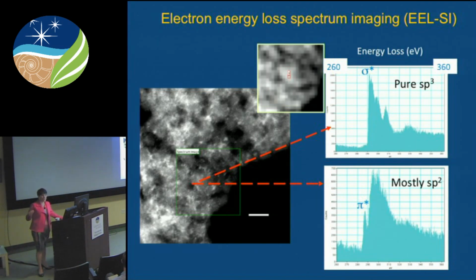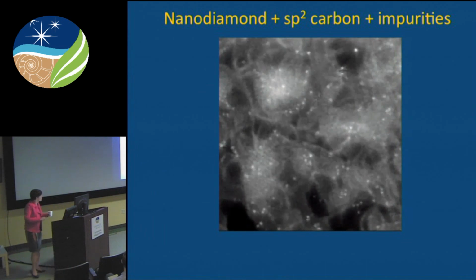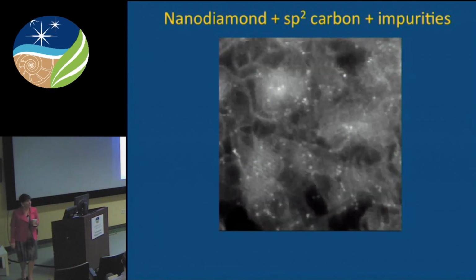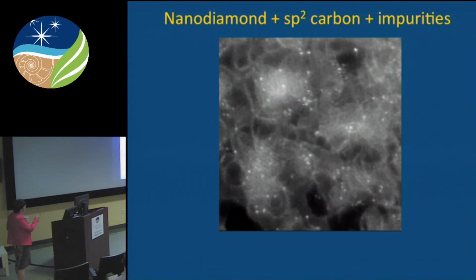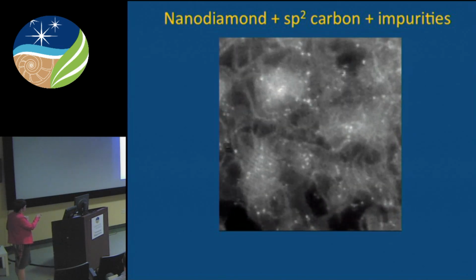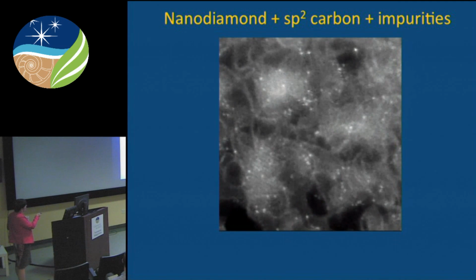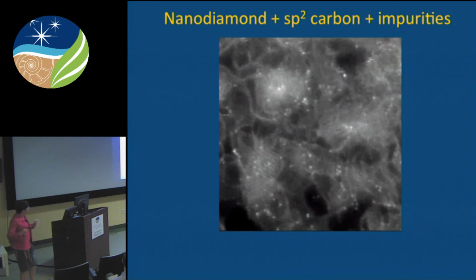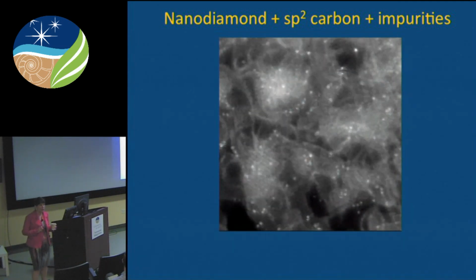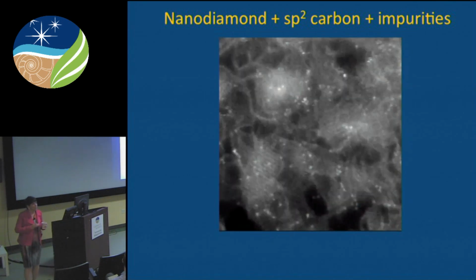Out at the edge, it's mostly sp2 carbon. You see that in a lot of detonation diamonds as they form a graphitic-like shell, but in this case there's actually sp2 carbon that extends way beyond the edges of the diamond, and in some places the diamond appears to be fully terminated as a fully sp3 product, which means probably there has to be hydrogen there. I don't think you can terminate with straight carbon bonding and maintain sp3.